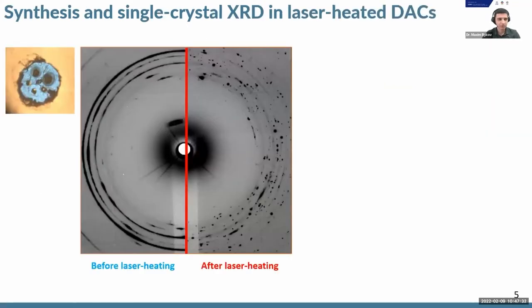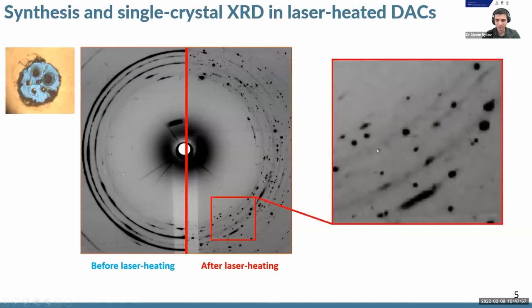In our studies, we usually use a single crystal X-ray diffraction approach. In a diamond anvil cell, we would put several pieces of our reagent embedded in the pressure transmitting medium, which can also be used as a reagent. Before laser heating, we see the nice powder pattern. This is the powder pattern from iron embedded in nitrogen. After laser heating, we see the formation of multiple very sharp single crystalline spots, which are quite well separated from each other.